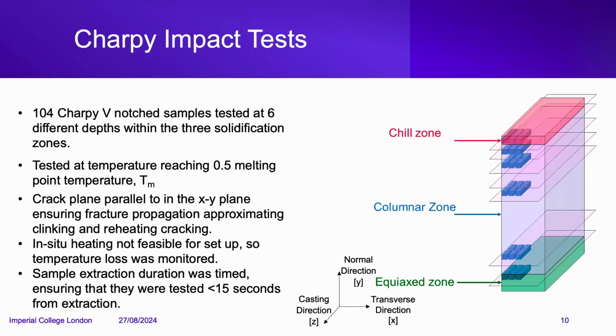And that's exactly what I did. Some Charpy V-notch samples were extracted from 6 different depths in the slab, encompassing all 3 solidification zones. These were tested from room temperature all the way up to the melting point temperature of the steel. And these were oriented so their crack plane is parallel to the XY plane, mimicking the propagation and crack plane of clinking and reheating cracking.